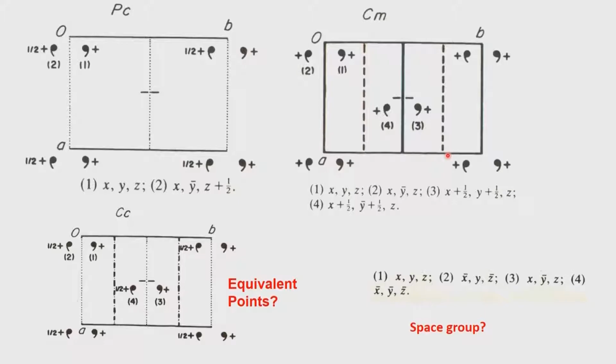And if we look at the situation where we have a C centered lattice with a C glide, then we generate equivalent points which will result in the presence of an N glide, which is at 1/4 and 3/4. So, more additional symmetry elements start cropping up depending upon how we combine the lattice symmetry with the point group symmetry. The flexibility allowed for the objects which go into these space groups is restricted, because it has to satisfy the other symmetry elements which are also developing.